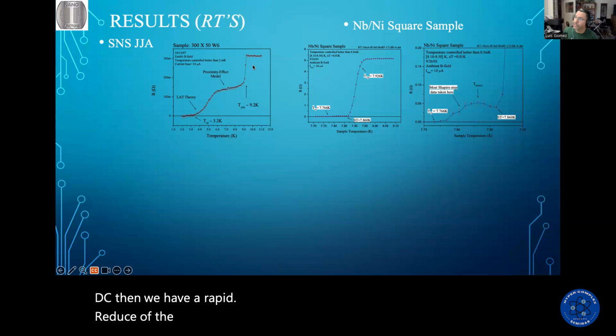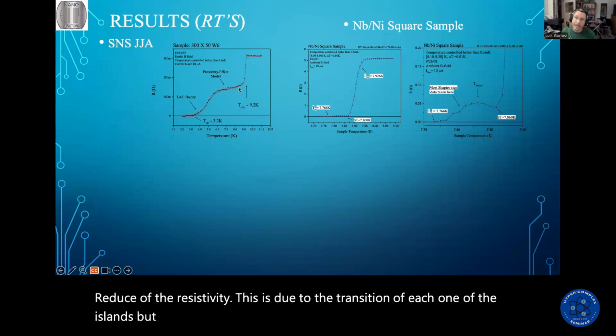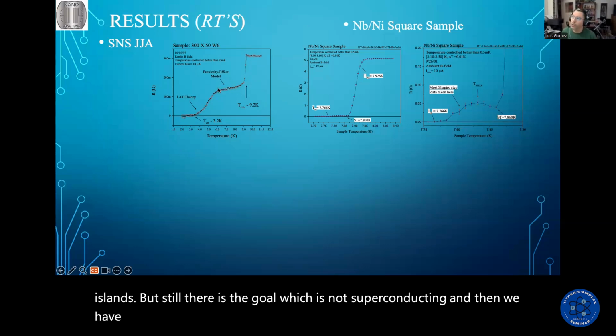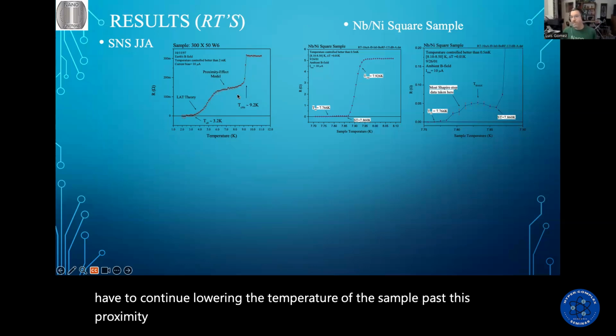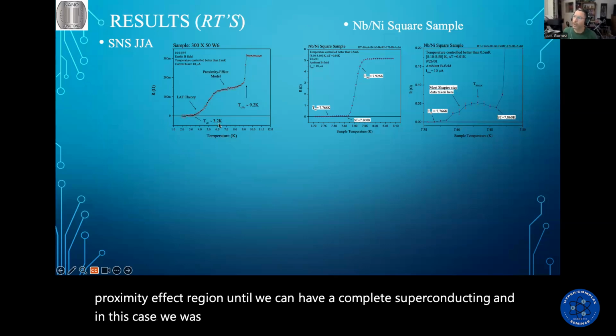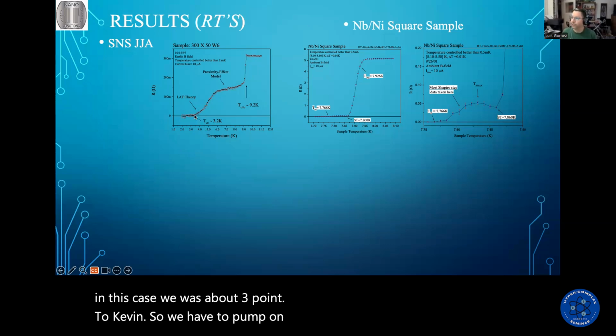This is due to the transition of each one of the islands, but still there is the goal, which is not superconducting, and then we have to continue lowering the temperature of the sample past this proximity effect region until we can have a complete superconducting. In this case, it was about 3.2 Kelvin, so we had to pump on the helium-4 system to achieve this.